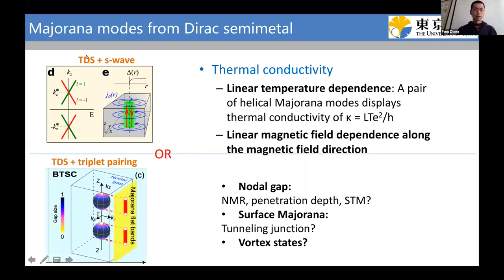For the superconducting topological Dirac semimetal, if it's s-wave, then we expect Majorana modes along the vortex line. We may see some signal from thermal conductivity. We will see linear temperature dependence and linear magnetic field dependence. If it's triplet pairing, then due to the nodal gap and the flat band, we may see some evidence from NMR, penetration depth, STM, or tunneling junction for this flat band.